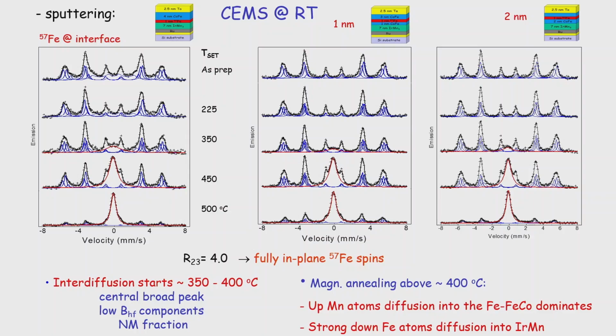The question is because in my experience, generally we have verified that there is no strong diffusion up to 460 in 3D elements generally. It depends how you prepare, it depends on the quality of your sample. There are two things that are very hard to compare. First is the temperature in your sample, in these preparation systems, because it depends very much where your thermocouple is. Be careful comparing growth temperature and measurement temperature, because it depends very much on your system. Your 500 can be very different from my 500.